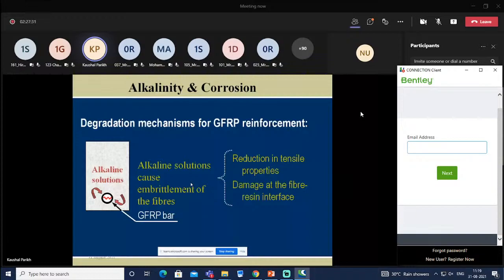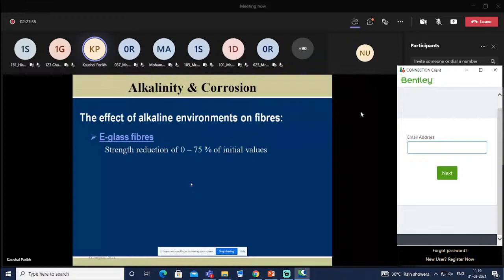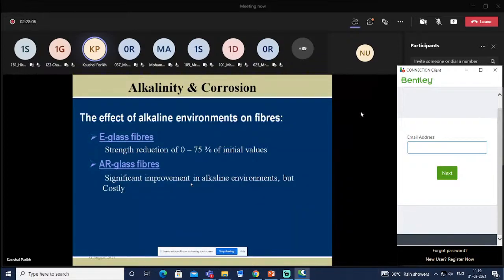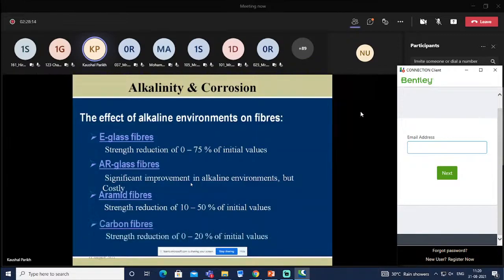Now, if we consider the individual fibers and their effect with respect to the alkaline environment, specifically for E-glass fiber, the strength is reduced by up to 75% in comparison with the initial values. For AR glass fibers, as the name suggests, they are alkaline resistant glass fibers, with significant improvement in the alkaline environment, but definitely at a higher cost in comparison with E-glass fibers. Aramid fibers show strength reduction up to 50% of the initial values, and carbon fibers are much less affected by the alkaline environment, with a reduction of strength up to 20%. But as I suggested, as written over here, further research is needed.